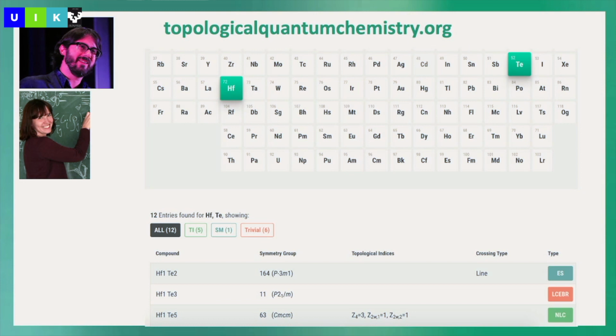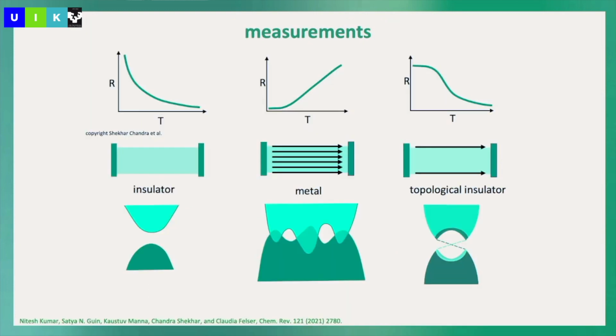And I think the next step is what Charlie already said. We have to go to correlated systems, and I think many people are working on this. You really have to treat oxides with a grain of salt, because many people are super excited about oxides, but you have to go beyond the single particle picture. And I still think in oxides we probably find a topological insulator which has an even larger gap and is less sensitive to disorder than bismuth selenide, for example. Anyway.